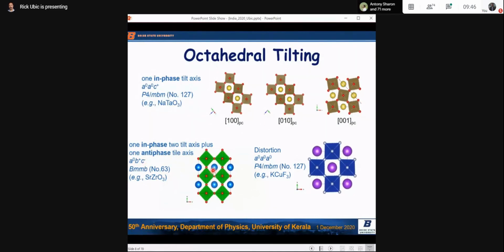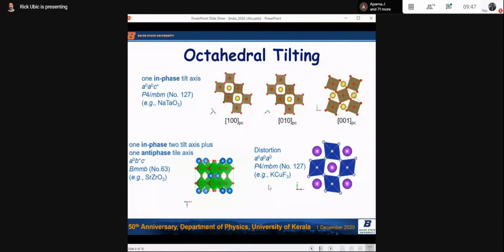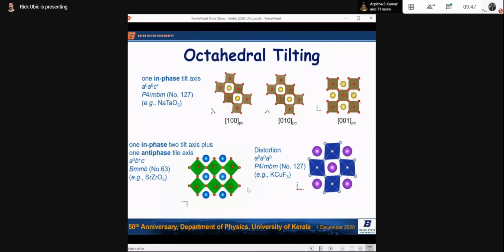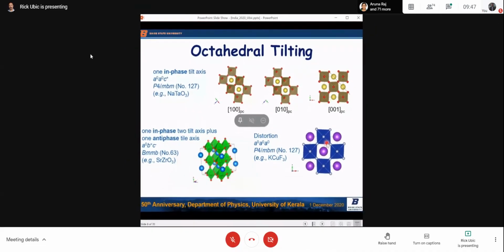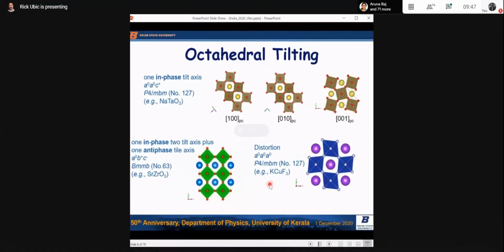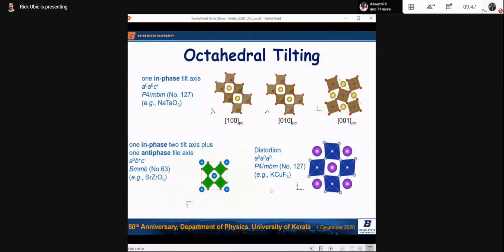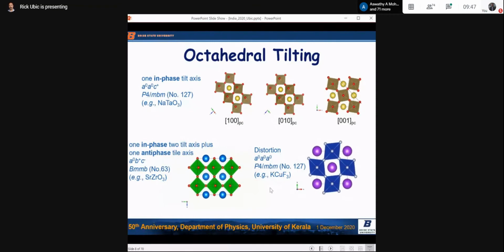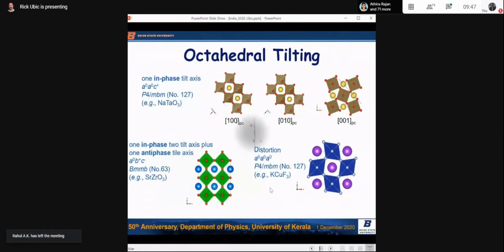And then finally, something else that can happen is distortion of the octahedra. So there's no tilting involved. This shorthand, if you understand it, tells you there's no tilting about any of the axes, but it's still not cubic because they're distorting. You can see how they're distorting. So there's another example of what can happen with perovskites. In general, they are not cubic, and in general, they are tilted. And the lower the tolerance factor, so basically the smaller the A site, the more tilted they're going to be.